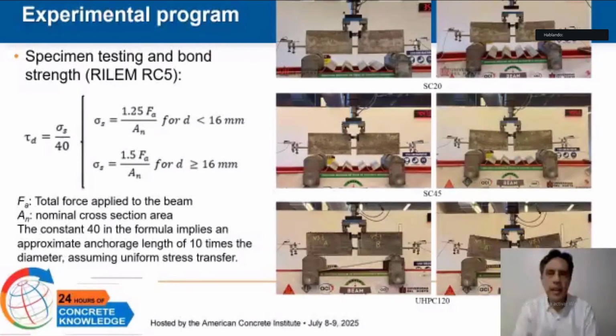On the left side of the slide are the expressions used to calculate bond stress tau, which are derived from the applied load Fa and the nominal bar surface area An. The constant 40 in the denominator reflects an assumed anchorage length of 10 times the bar diameter, providing a uniform stress distribution model as per RILEM standards. Altogether, this comparison highlights how both material properties and structural configuration govern the bond performance of GFRP bars in high-performance concretes under bending conditions.